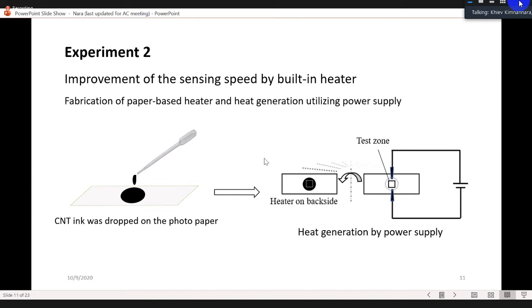So because of this, I came up with a new idea to fabricate a heating system for accelerating the enzyme reaction. First, carbon nanotube was spotted on the photo paper, and then it was dried. When it was dry, on the backside of the CNT heater, I fixed filter paper, which is designed as a test zone. After that, it was connected to a power supply to generate heat by applying different voltages. Okay, next slide.